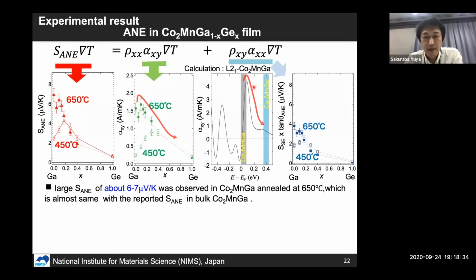However, if our pure Co2MnGa had the same Fermi level position as the theoretical Co2MnGa, actually alpha XY must be very, very small. But as you can see, we observed a relatively large alpha XY even in the pure Co2MnGa.